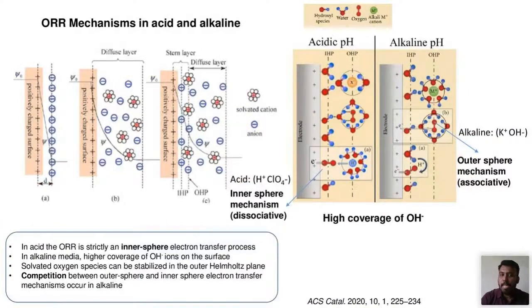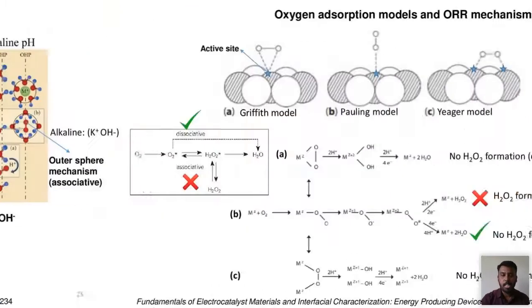So ORR mechanism in acid and alkaline, as I pointed out before, the double layer will be formed, and based on where your oxygen molecule is bonded or at which position it is bonding, it can determine your inner sphere mechanism or outer sphere mechanism, whether it is acid or alkaline. Whenever you have an oxygen molecule adsorbed directly on the electrode surface, then it will contribute to the inner sphere mechanism, and it can reduce oxygen directly to water without forming hydrogen peroxide. Then if it is in the outer sphere or outer Helmholtz plane, then it will generate the hydrogen peroxide.